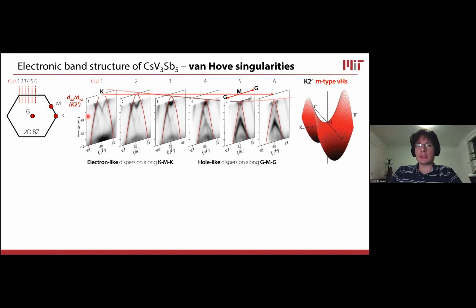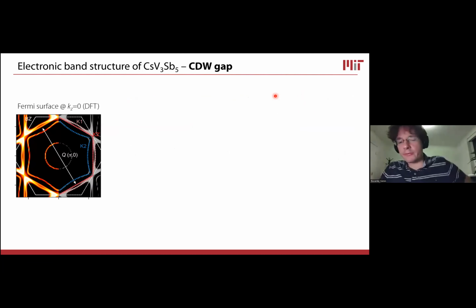And that's exactly what we see. So we have this band that has a maximum at K, and that maximum disperses downwards, and then it goes back up. So the signatures are very clear. And when we look at the Fermi surface, remarkably, the Fermi surface presents the conditions for nesting for all these three bands.